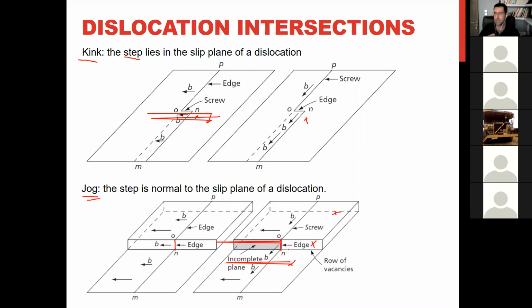This is one reason for strain hardening, because when you activate several slip systems, obviously these dislocations intersect each other, and they can make this kind of lock. So the dislocation movement will be more difficult. From the stress-strain curve of FCC, at the beginning we have strain hardening. One reason is that we have several slip systems activated, so dislocations easily cross each other. They make such locks, and the deformation is more difficult, and we call that strain hardening.